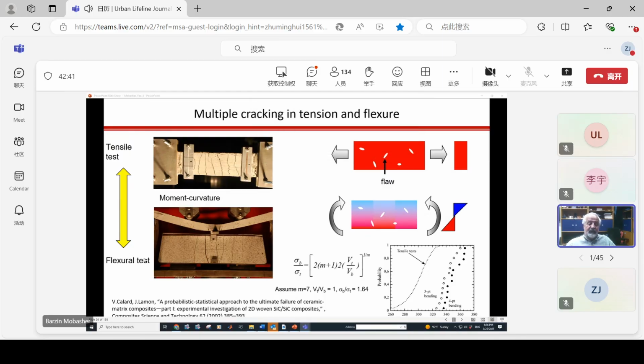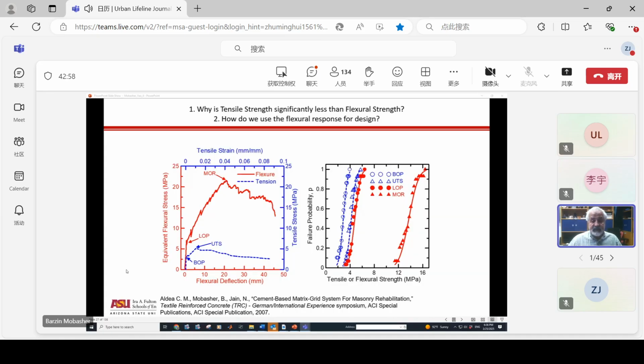But we have a big problem with converting data from tension to flexural test. And that is an important parameter for us to look at. Why do our cement-based materials show a higher strength when we test them in flexure? Luckily, a lot of our failure designs, such as beams, are in the area of flexure. So that's where we look.